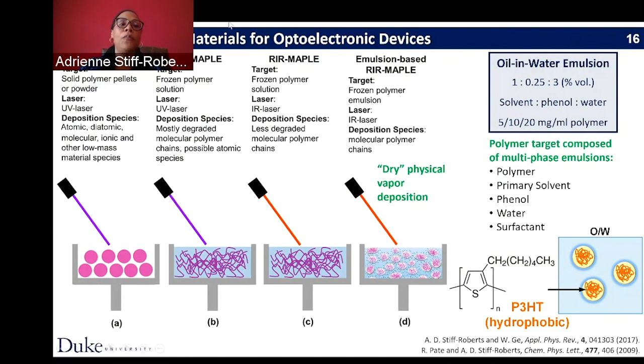So people first started trying to do pulse laser deposition. So sort of the traditional approach where you had a solid target made up of polymer pellets or a powder, and you hit that solid target with a UV laser, a high energy ultraviolet laser. And the idea is that you would then sublimate the target material, and then it could reconstitute on the substrate. The problem is that when you do this with polymers, you're not getting the polymer material that you synthesize. You're getting all types of different species, atomic species, diatomic, molecular, ionic, or other low mass species. It's not the polymer that you synthesize with the properties that you designed.